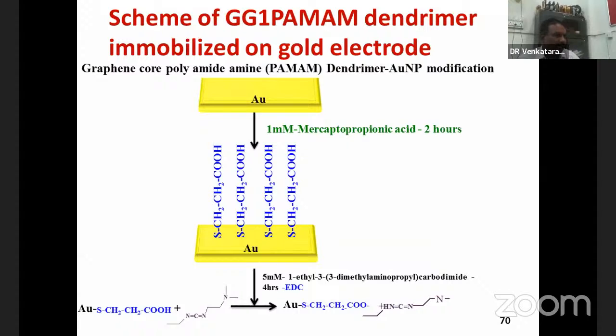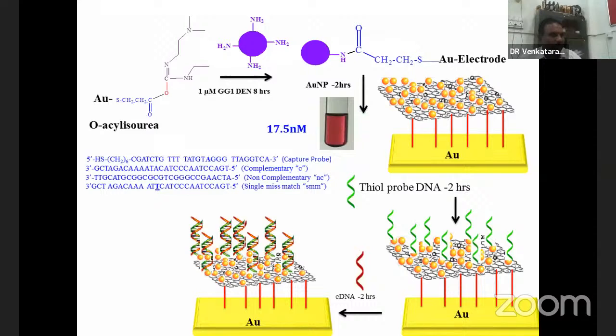For that, we attach the graphene surface on top of the gold layer using some intermediate molecule. Here we use mercaptopropionic acid, on top of which we also put, because we want to have a covalent linking between the single-strand DNA through a gold nanoparticle. Adding the gold nanoparticle on top of the graphene or graphene oxide will enhance the reactivity, the active reactive sites, so that you can enhance the hybridization event or signal intensity.